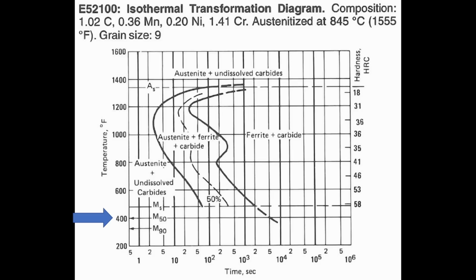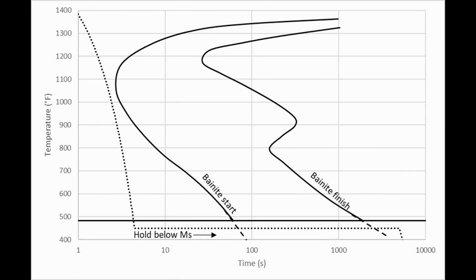And then there is this dashed line extending down where they are estimating how long it should take for full bainite transformation after the martensite formation. Now, this is another interesting thing. So we discussed how if you do not fully transform to bainite, you would air cool and form martensite, and then that martensite should be tempered if you want to make sure you don't have brittle, untempered martensite. Another way of having a partial martensite, partial bainite microstructure is to quench under martensite start, but not so low as room temperature, and then you've already formed some martensite, and then you hold to form bainite. And during that hold, you're also tempering the martensite that you initially formed.